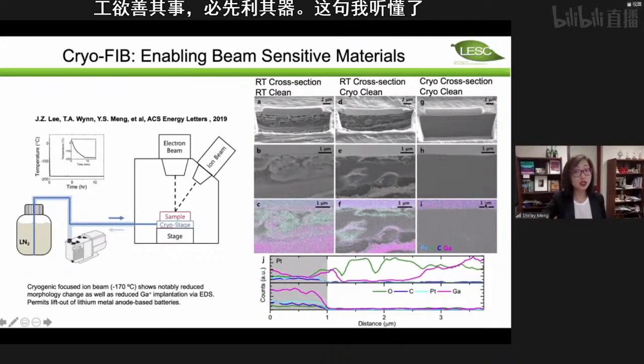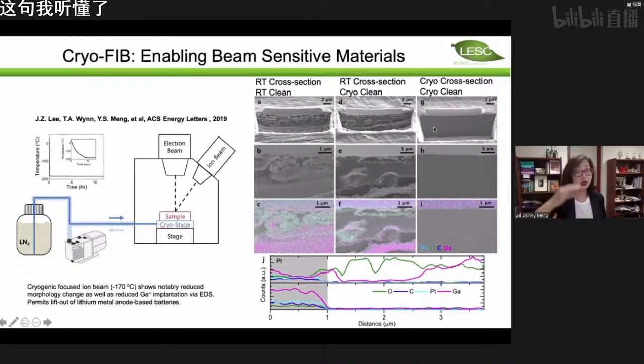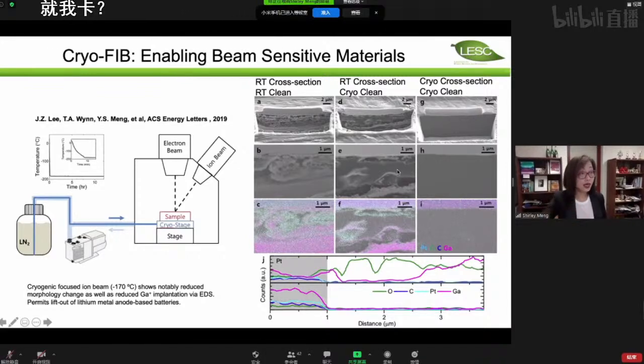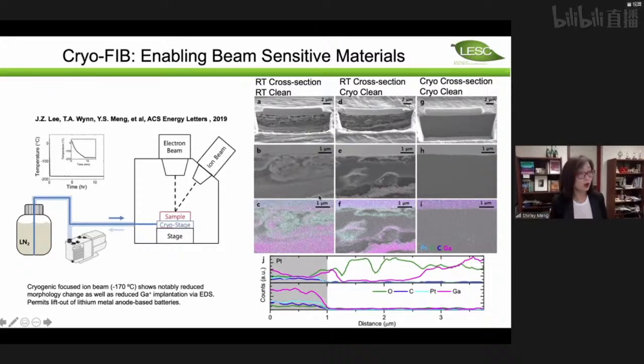If you actually do cryogenic conditions, the kinetics of the interaction will be dramatically reduced. And that's where you can actually get a quite clean surface of the lithium metal. This lithium metal is, of course, just a metal sheet, so it is supposed to be dense, very smooth and very nice looking. Now, why is this tool so important? Because electrochemically deposited lithium does have a lot of pores and tortuosity. So if your tool already interferes with the lithium, you cannot observe lithium very well. That's a very easy logic to follow, right?